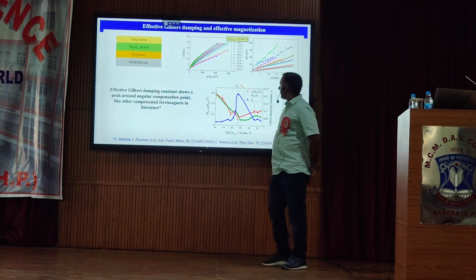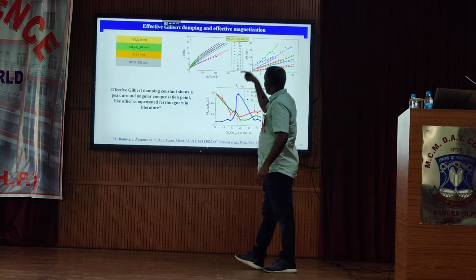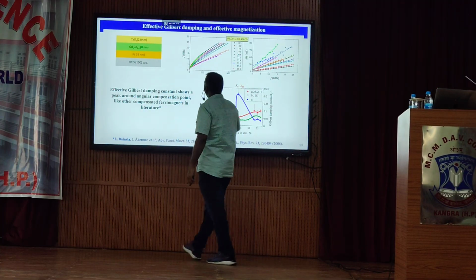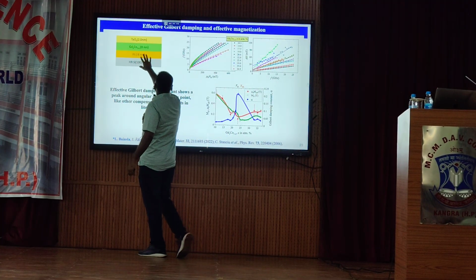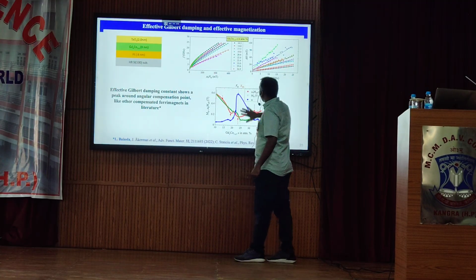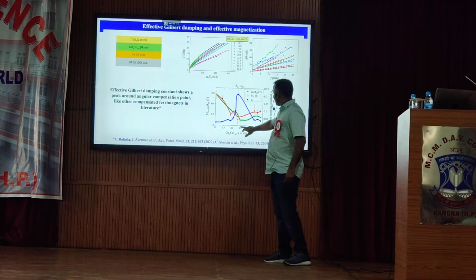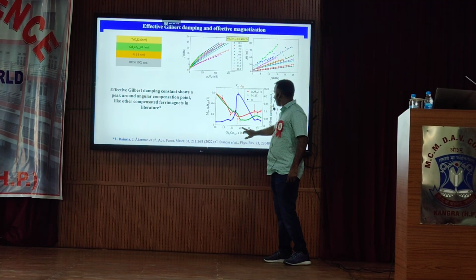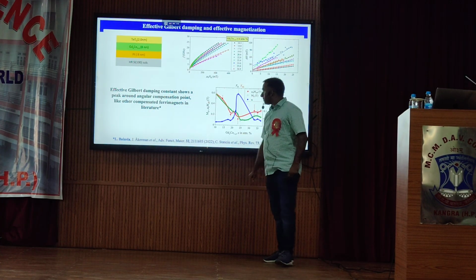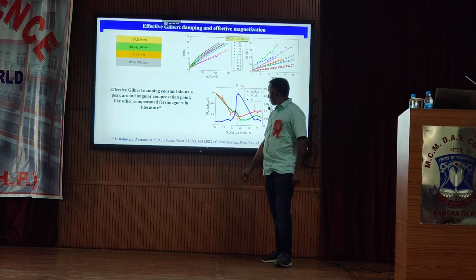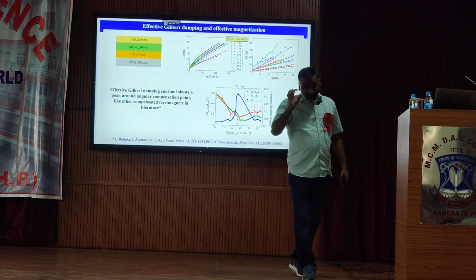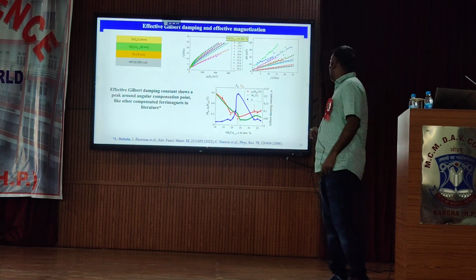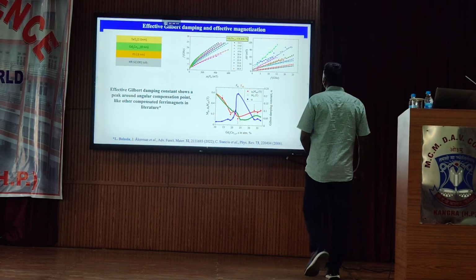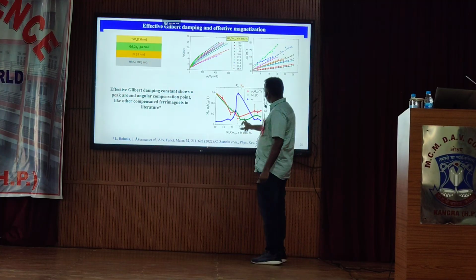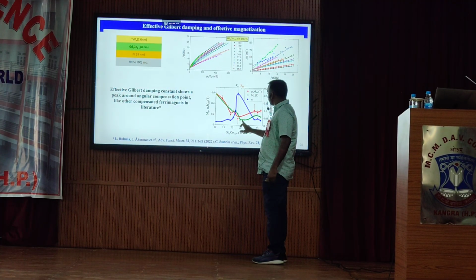After that we again go for different compositions. The previous results were on one composition, then we choose different compositions of our system. You can see the final results here. Again, near 25% of gadolinium, we have a minimum in saturation magnetization and effective magnetization. This again confirms that near 25% gadolinium percentage, we have really compensated ferromagnets, where we have almost vanishing net magnetization.